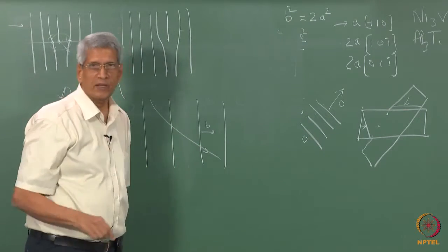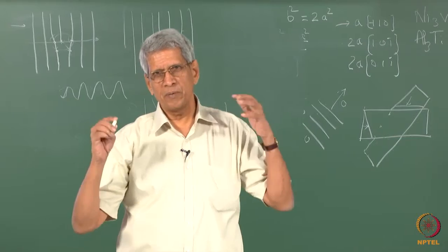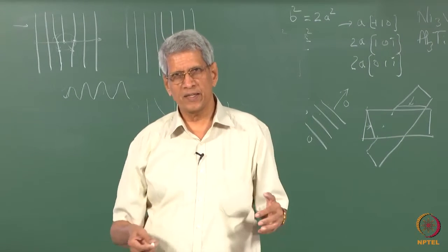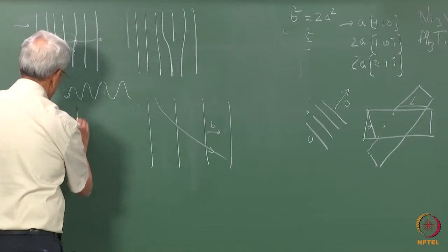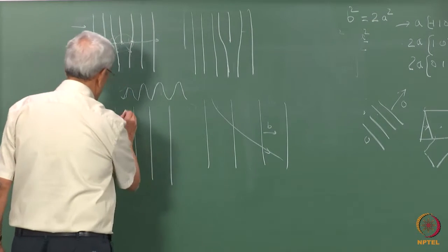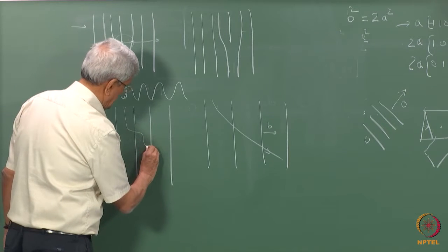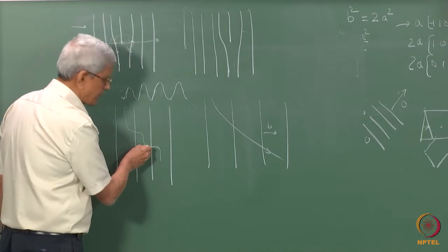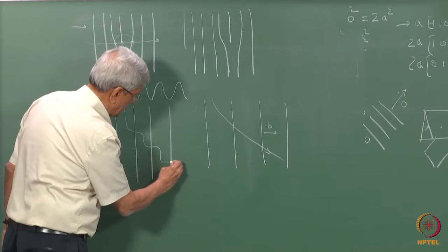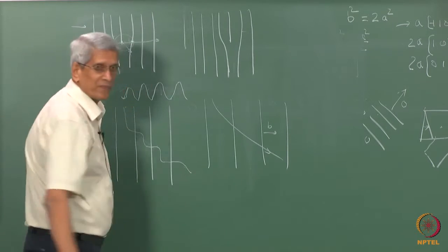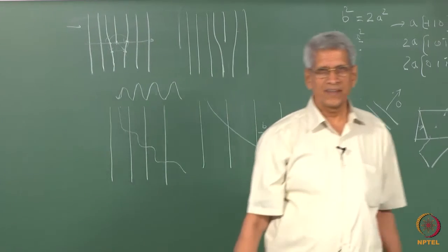If you look at the energy of the dislocation core, it is going to vary. So it's not in a minimum low energy configuration. The way in which it can assume a low energy configuration is that part of it remains like this, a step is created, it comes like this, another step is created. So only the minimum part of the dislocation line has to be in the high energy region. If a step is created like this and it moves, this is equivalent to this one. And all these are nothing but a kink in the slip plane.